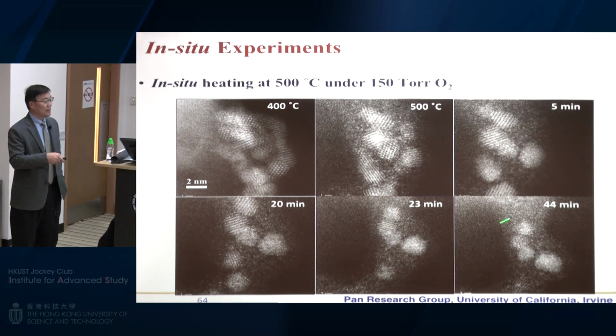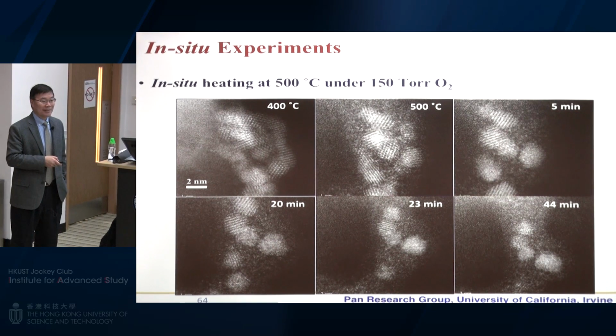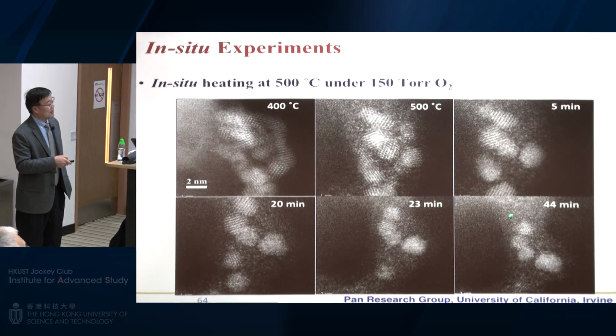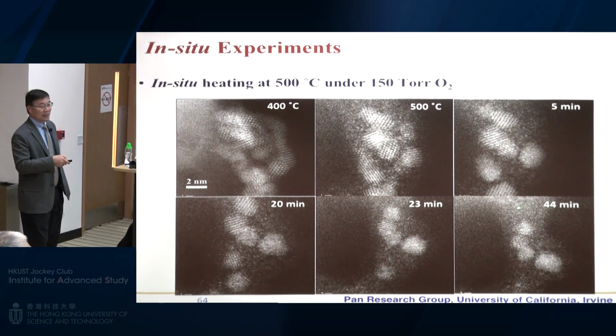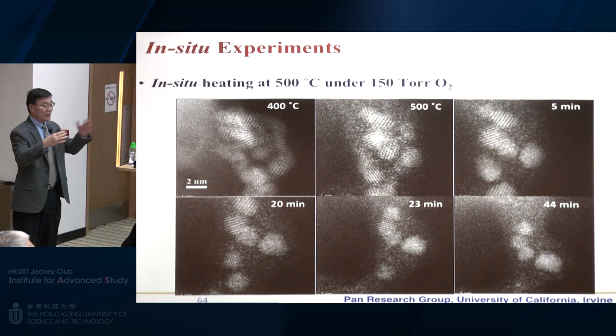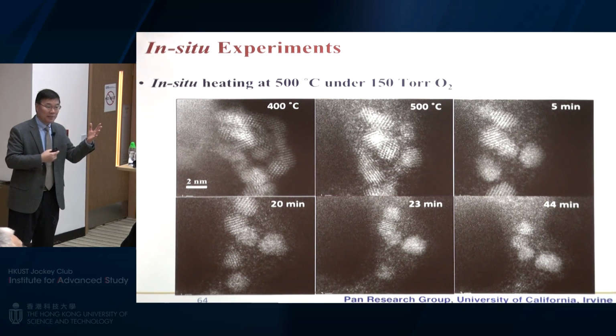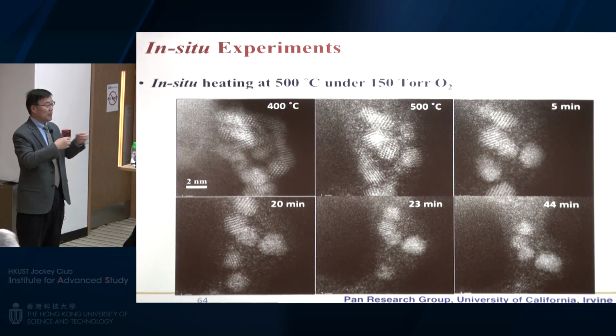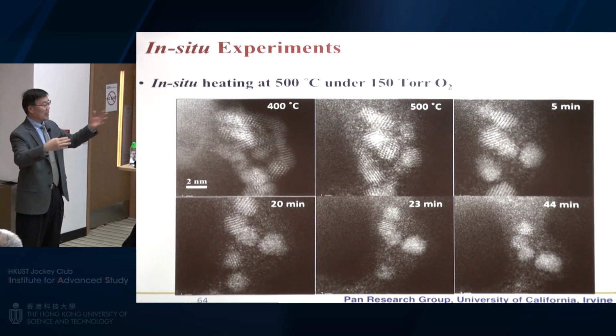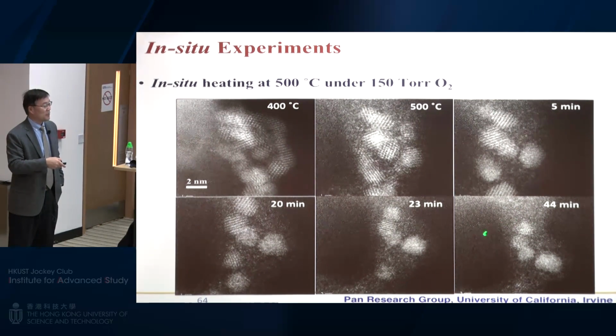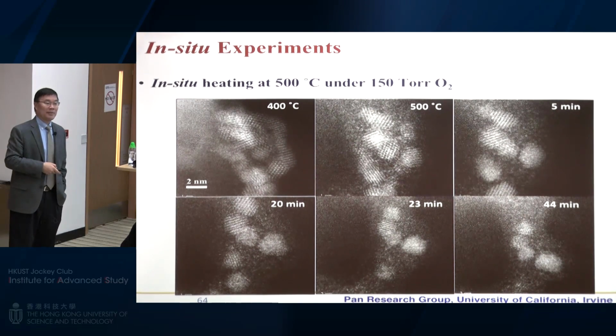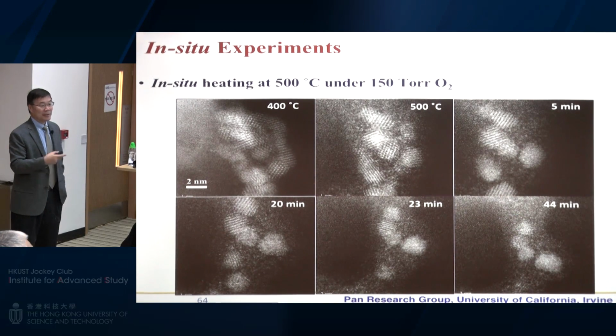What are your hunches? What are your best guesses of what this atomic cloud is? I guess iron oxide should be stable because this is an oxygen atmosphere. Platinum will be volatile, so a platinum particle probably just dispersed, and before it reacts or forms other kinds of phases, it is just floating around, very mobile, moving around. You can see that each time it is not staying in the same area. So the integration time is too long to capture it. Yes. It'll be great.